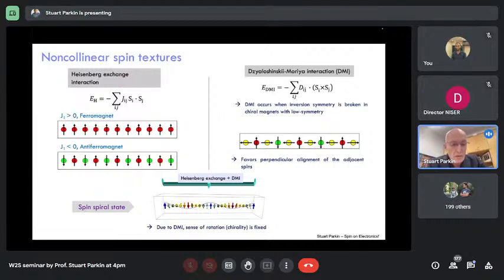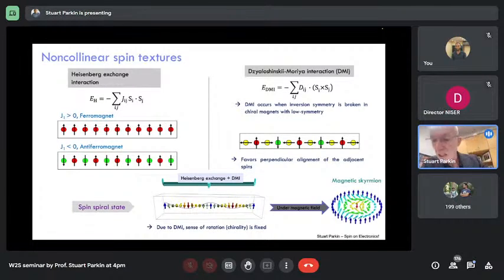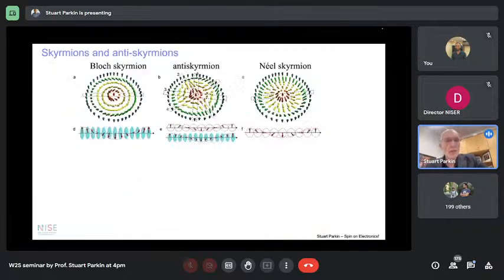This leads to, for example, spin spiral states, as shown at the bottom, where the magnetization then, by combining Heisenberg plus DMI, forms a spin spiral. And this can then lead to something called a skyrmion. This was discovered 10 years ago by Christian Pfleiderer in Munich, here in Germany, where he showed the formation of these very interesting circular objects and arrays of these objects by neutron diffraction in a so-called chiral material, a B20 manganese silicon material. I don't want to talk about that. I want to briefly mention these other objects.